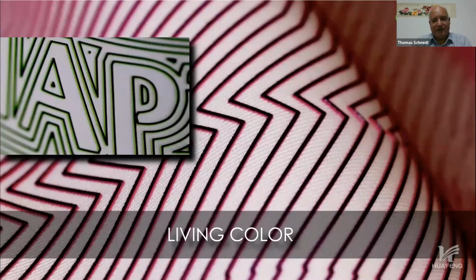Another exciting color effect is the living color. We call it living color. These are basically two colors printed on top of each other. The base coat, which usually contributes most of the thickness of the coating, we usually print in a very bright color pigment like magenta or a bright green, and then on top, the surface color coat, we put usually a darker color. When you move these materials, depending on the viewing angle you look at, this second color on the base coat will pop up, and it looks like the color is permanently changing during movement.